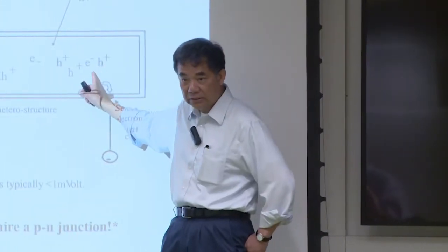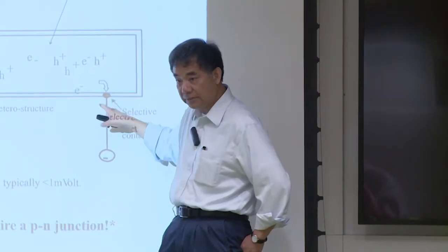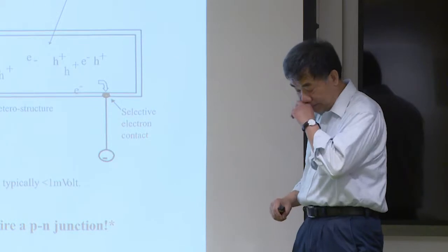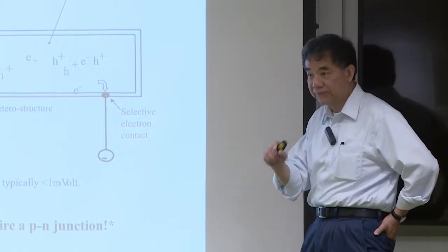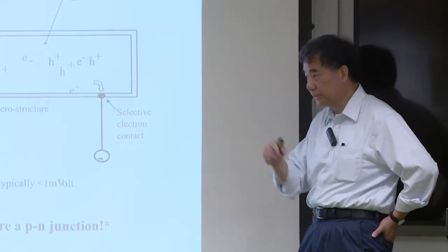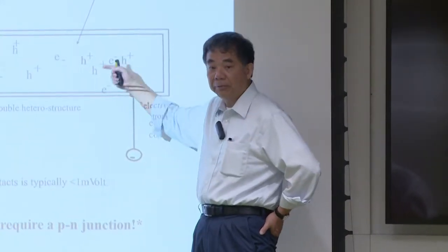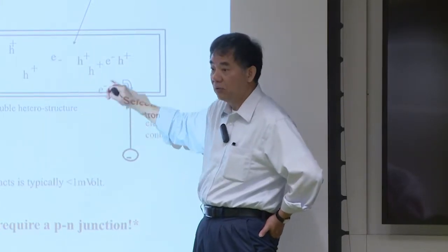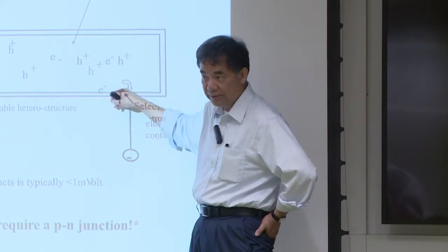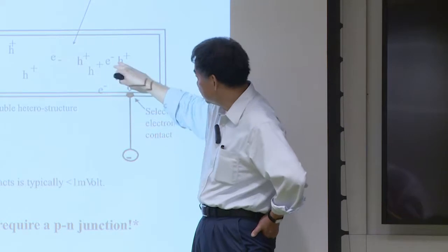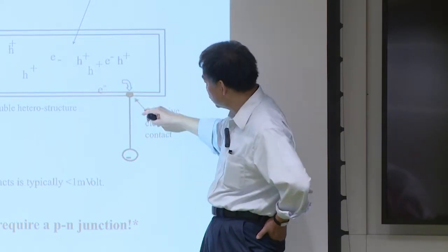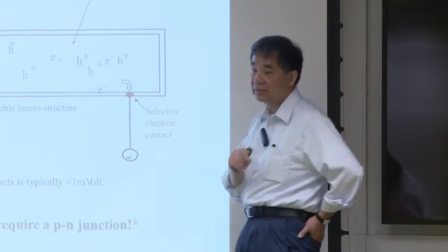So the key, let's come back to the model. The key of this chart is whether the carrier lives long enough. If the carrier has a short lifetime, it will die before it is extracted. However, in Eli's theory there is an important part: high fluorescence. That actually defines the difference between an inorganic solar cell and an organic one, which Professor Gangli is a world expert on. If the electron and hole unfortunately recombine, there will be fluorescence, and strong fluorescence is required. What happens to the photon it generated? It should be reabsorbed, forming so-called photon recycling. The fluorescence will excite the carriers again, so the carrier basically never dies. And if the carrier has a long enough time, it will find its home and be extracted. That's the key.